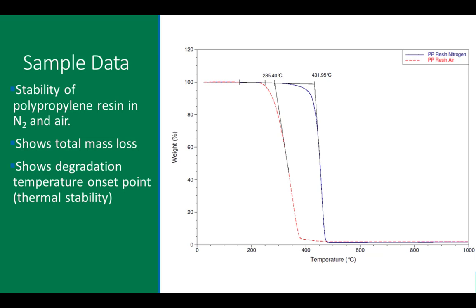This is related to thermal stability. You don't need to have the nitrogen plot, but the air plot — the red one — is showing the thermal stability of your sample. You would probably want to stay well below 250 degrees C in order for your sample not to degrade in a normal air environment.